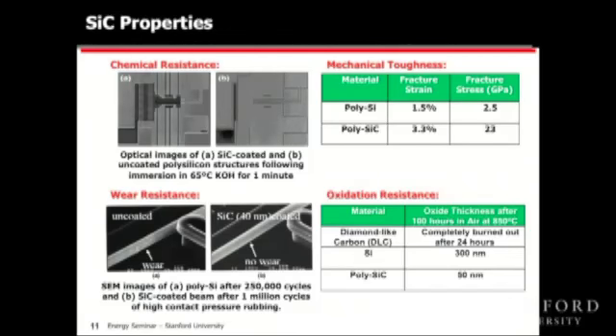After 250,000 cycles of rubbing contact, you can see the uncoated device shows wear, whereas the silicon carbide coated device, with a very, very thin coating, 40 nanometers, shows no wear. And silicon carbide is actually used to reinforce drill bits material, so it's a very robust material. In addition, the fracture strain is much, much higher than silicon, more than double at 3.3%.